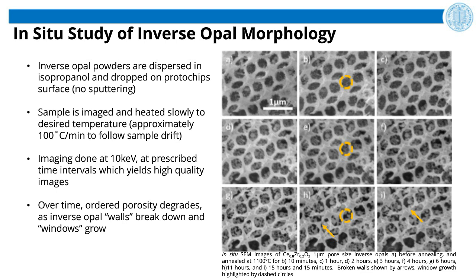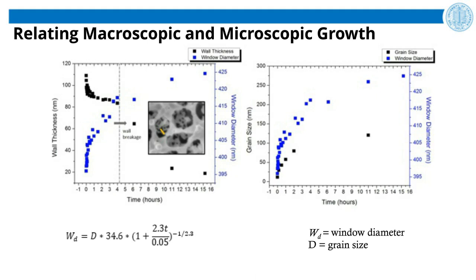Besides in situ SEM experiments, there were some ex situ experiments on measurement of the grain size change with heating. Those results were combined with these in situ results and allowed us to derive this empirical equation. The formula allows prediction of the microscopic behavior and lifetime of the inverse opal based on easily obtained ex situ measurements such as XRD for grain size measurement. So by measuring the grain size, we can predict what happens to the window of the opal structure, which is critically responsible for the conversion efficiency.